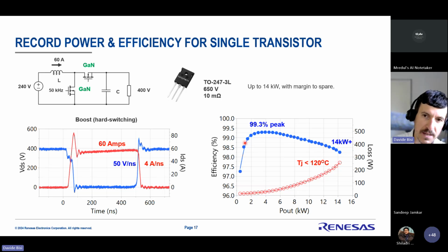And we got 99.3% peak efficiency, which is significant. And we were able to sweep all the way to 14 kilowatts of power. And the junction temperature was only 120 Celsius. So there was still margin for further increase in power. So to me, this one is a great result. Just with one transistor, we can have great efficiency up to a very high power density.